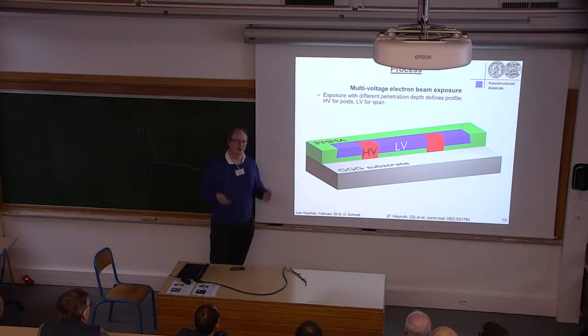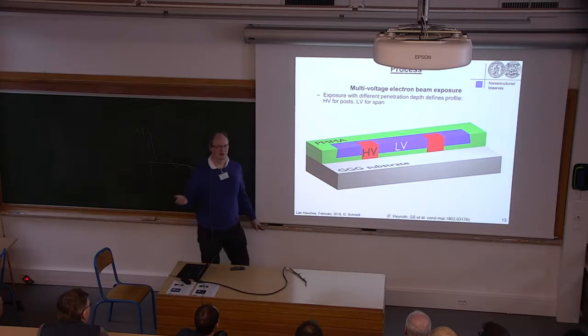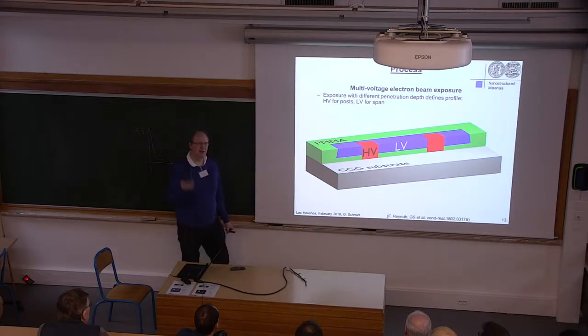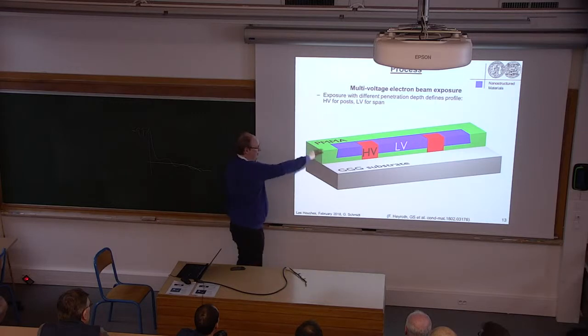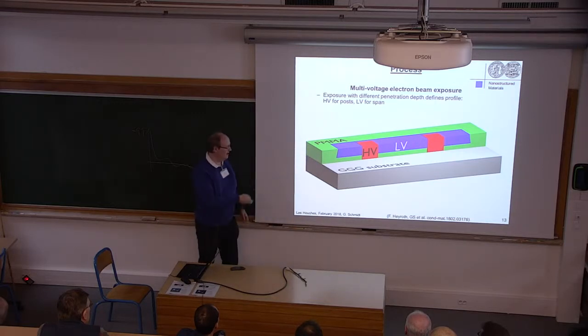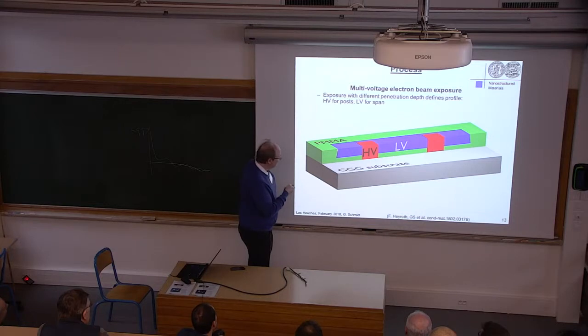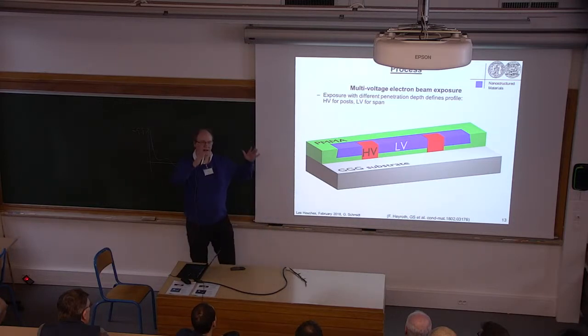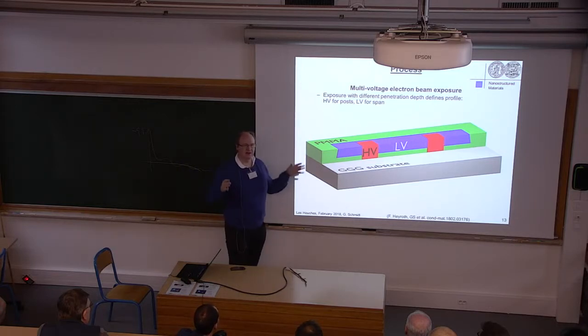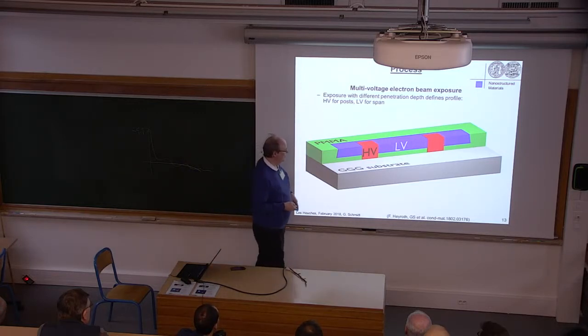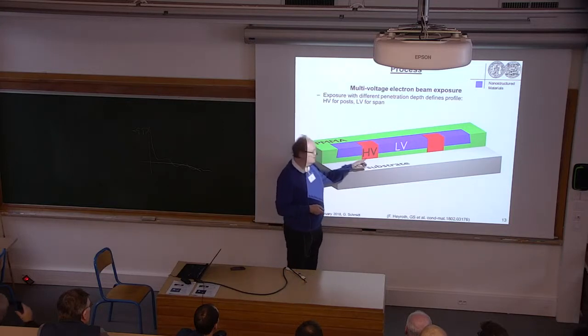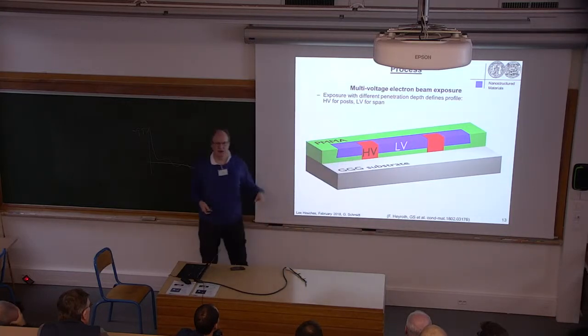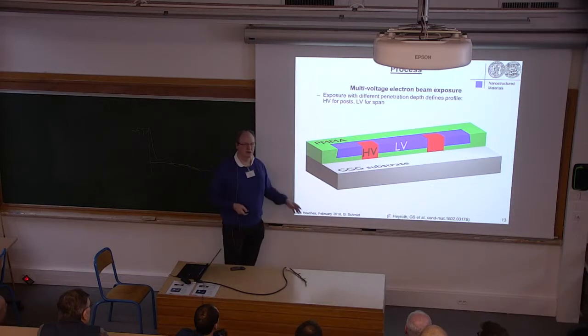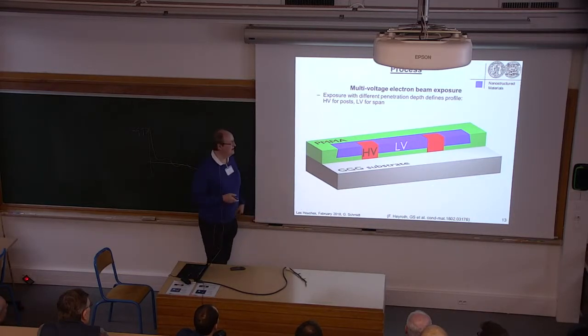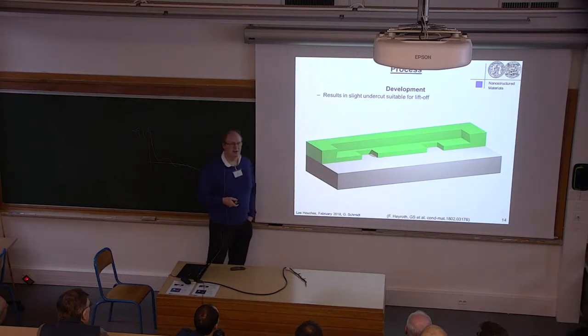So you can increase the dose, and increase and increase, but due to simple physics, the electrons cannot penetrate any further. So that means you can expose the top of your resist wherever you like. You will never get lower than this one. And also the sides, it's intentional that this is slightly tilted, because due to the scattering of the electrons, you get an undercut, which gives you this nice lift-off afterwards. And then you do high voltage exposure, where you go to the feet of the bridge, because 30 kV, they go 10 micron deep. So these are two completely independent processes, and after development, you get something like this.